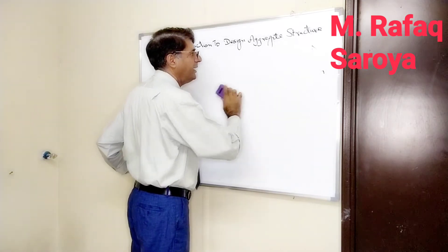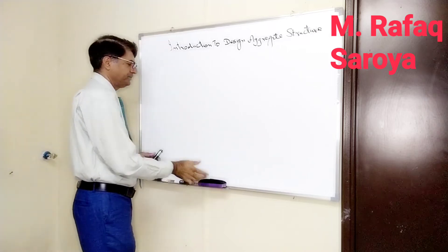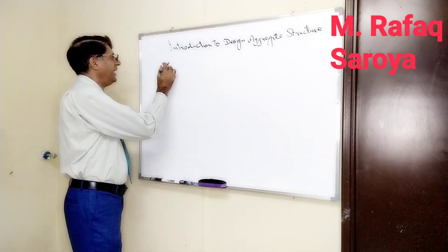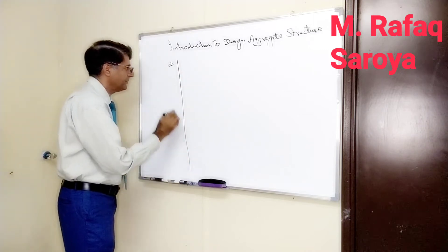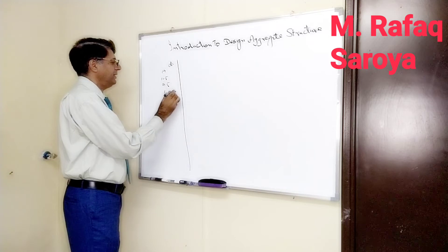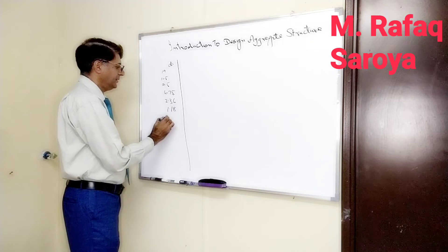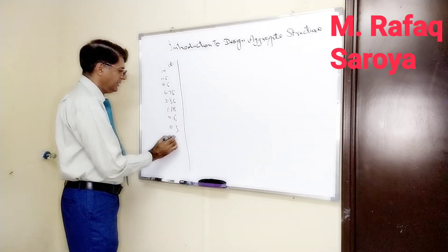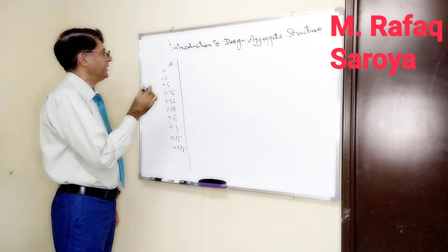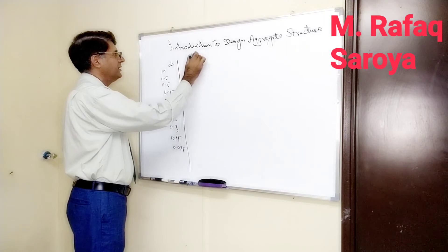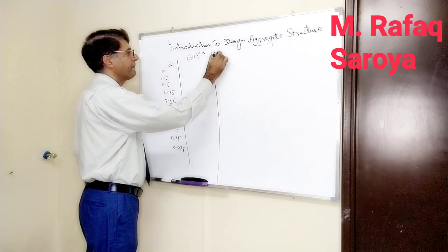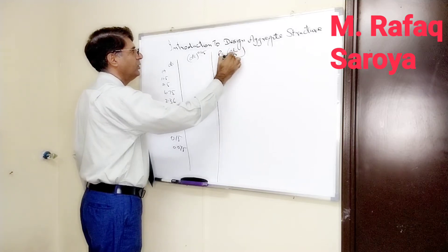All our discussion from the beginning is for the asphalt wearing course, which we have to design using the Superpave method. Here di means the different sieve sizes: 19, 12.5, 9.5, 4.75, 2.36, 1.18, 0.6, 0.3, 0.15, and 0.075 mm. These are the sieve opening sizes. When I take di to the power 0.45, I also calculate P using the formula (di/D)^0.45.